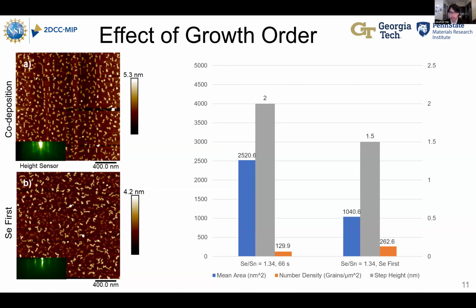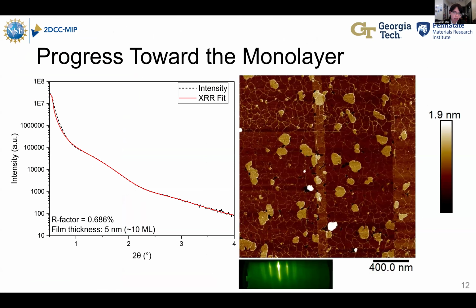What this suggests is that by having this additional selenium, this may provide a route to having more grains that may coalesce earlier. This is work that we're still analyzing, and it is still in progress, but these initial results are promising. It may lead to a way for us to get to that single monolayer, where we have a continuous layer across the substrate.